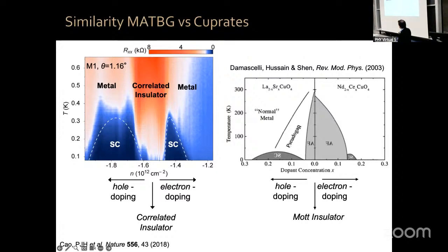You get a correlated insulator. If you dope with holes, you have a superconductor, an electrically tunable superconductor. You dope with electrons, the same. Now, despite some similarities between these two things, I should point out that this is actually quite a bit different, okay? There are many differences: this is a hexagonal lattice, this is a square lattice, and the energy scales are different, etc. But one important difference also is the fact that this is a theoretical phase diagram.